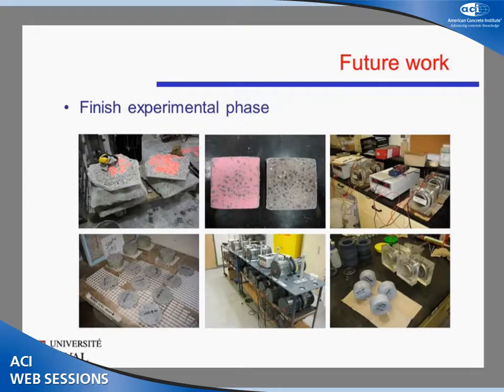So essentially, what's next? I just wanted to put a few pictures of what the project looks like in the dirt. In the bottom left, you can see what the drying test looks like. You have large 50mm samples and smaller 10mm samples. They're left in a 50% room to dry slowly, and you measure the loss of mass. Center bottom, you have migration tests. These large cells, about 2.5 liters on either side. The principle is similar to RCPT. And in the top, you have the imagery.